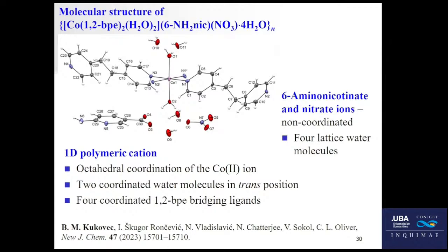So again we have a 1D polymeric cation, but it is different from the one I described previously. You'll see afterwards. The cobalt coordination is again octahedral. We have 2 coordinated water molecules, here in trans position, and this time 4 BPE bridging ligands. So this one, here and here, and that's only the cation. The anion is again just the aminonicotinate ligand, which did not coordinate, and some nitrate ions and lattice water molecules are also present there.